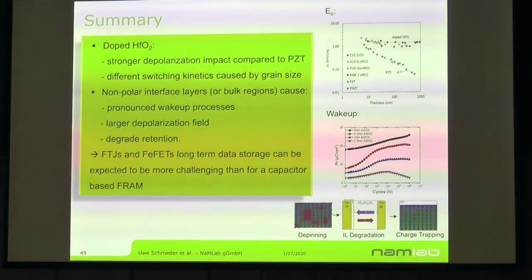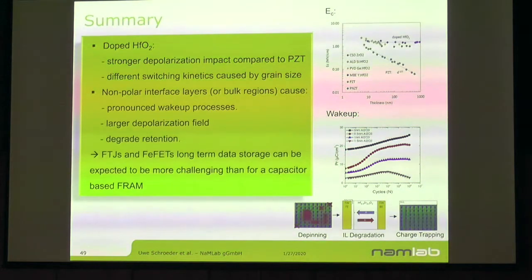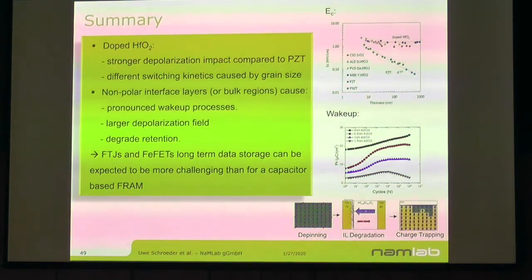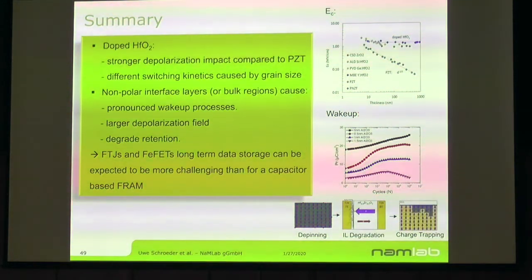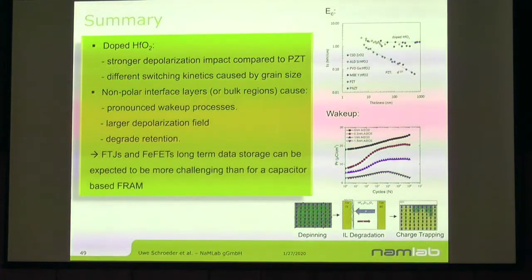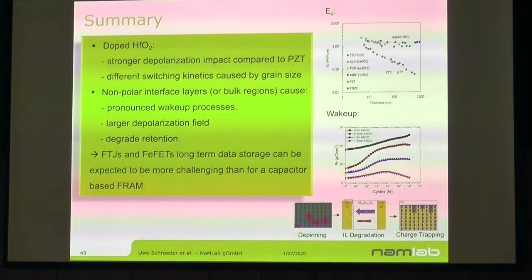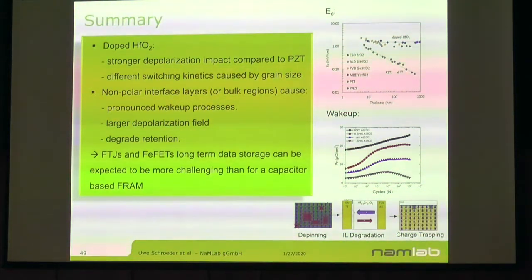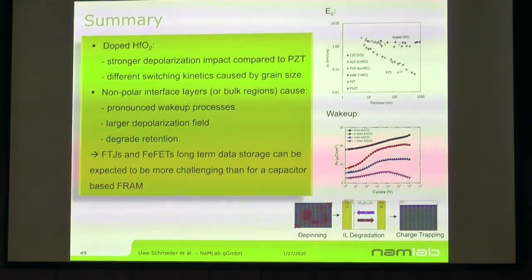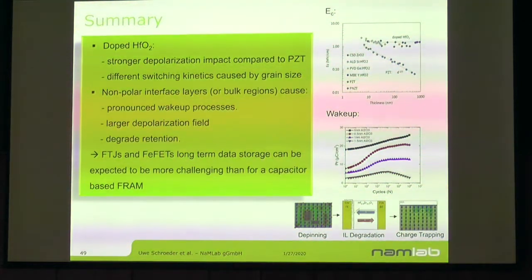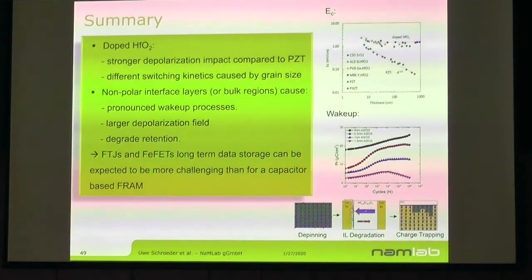Thanks. I'd like to ask what is known about domain walls, if they play any role in switching. Well, is there any experimental evidence for domain walls? The thing is, again, the small grain size. Typically domain walls are seen with PFM, and since the grain size is on the order of 10 to 20 nanometers, it's really difficult to see something smaller than these grains in PFM.